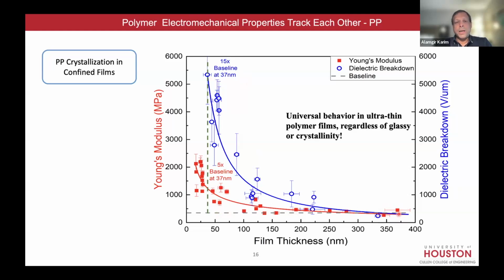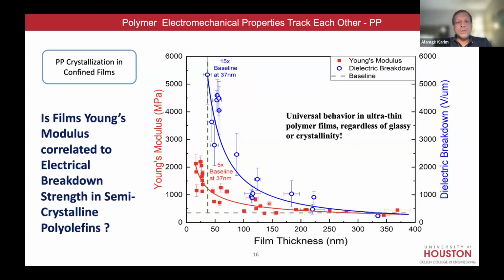All right. So the correlation to the modulus is actually very dubious, because I'll show you in the next example. All the glassy film, as you reduce film thickness, people have measured Tg as a function of film thickness and modulus and shown that it always drops below 100 nanometer because of film confinement.